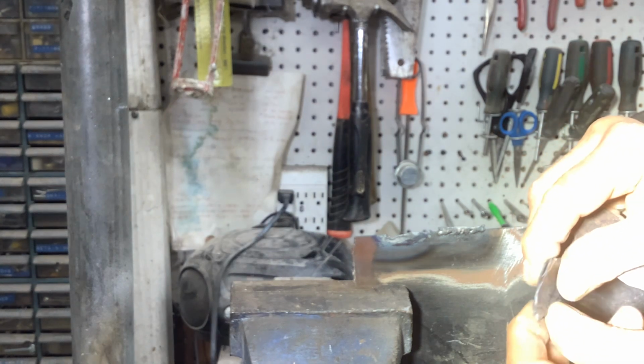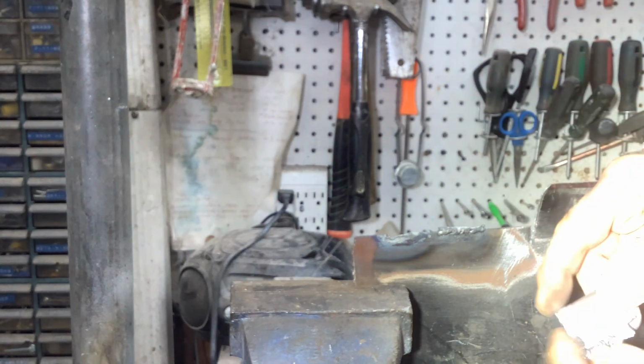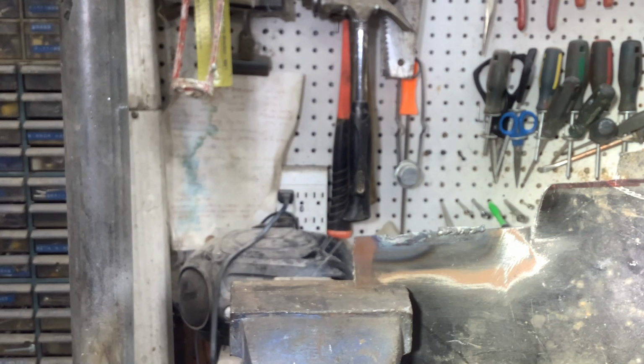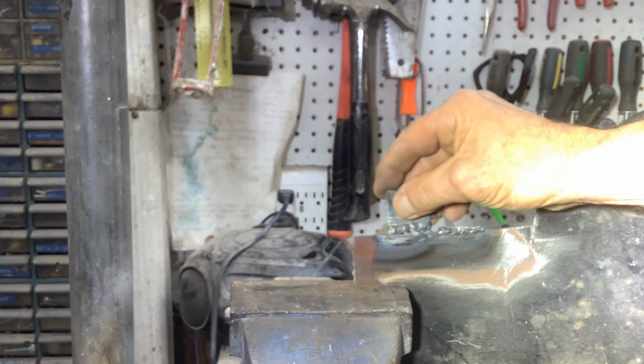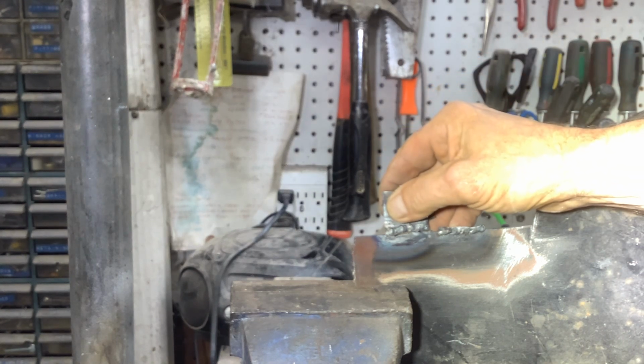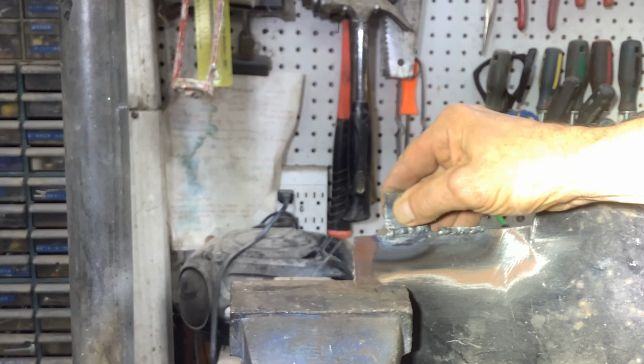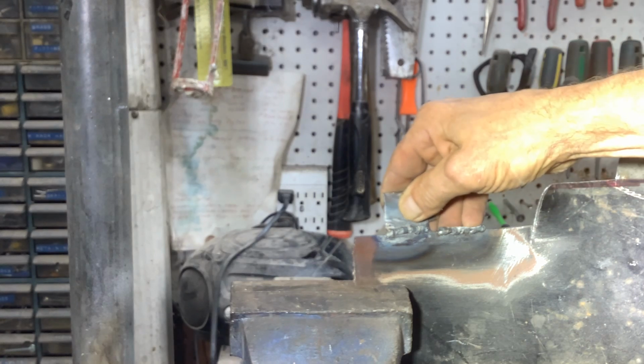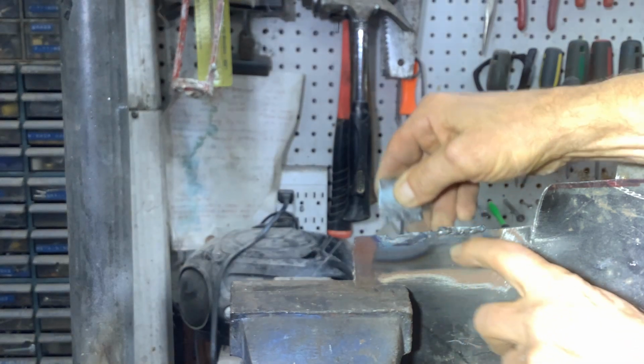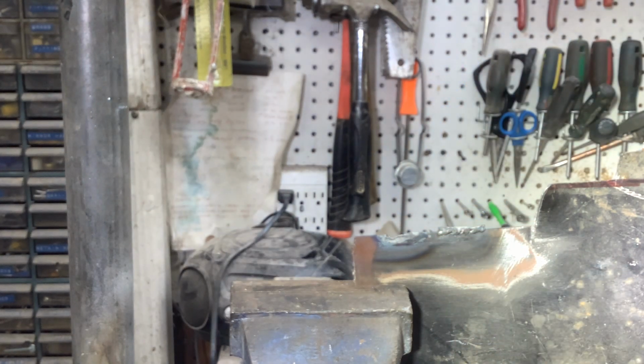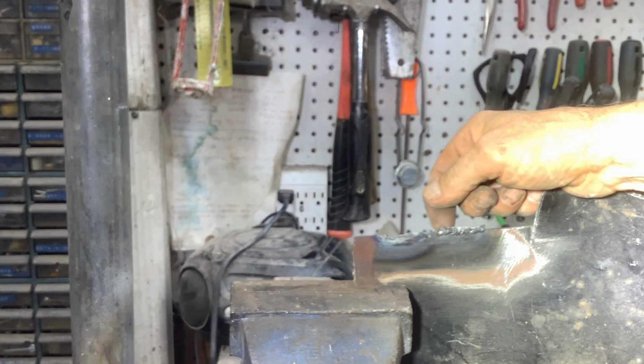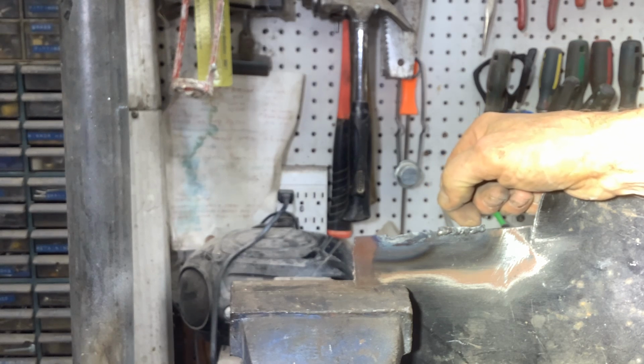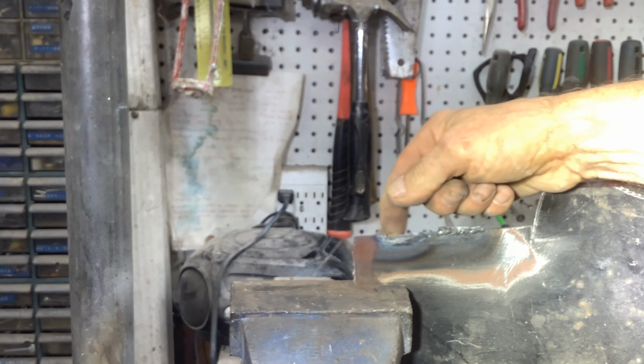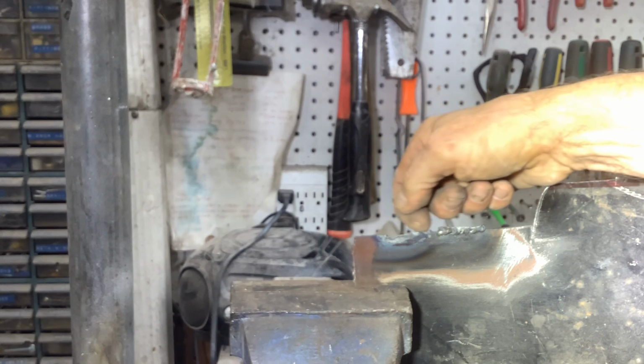Annealing softens the metal so it'll flex more. And if the process is used, it'll improve the strength of your welds, both on the tack weld and on the full weld across. The annealed weld held better and didn't break. The weld would have been stronger if it was welded from the back also. I only welded it from one side, so when you bend it back and forth, both welds are going to fail easily because they have a fracture along the back.